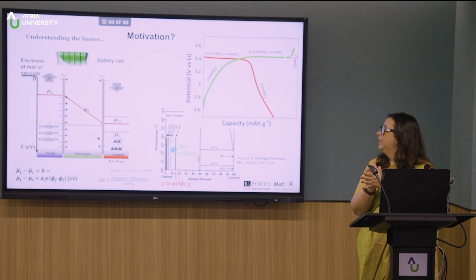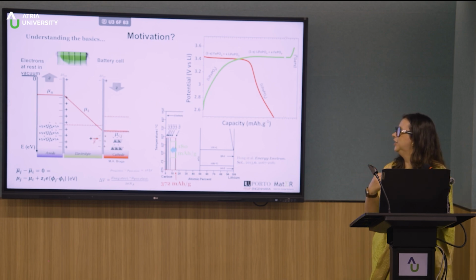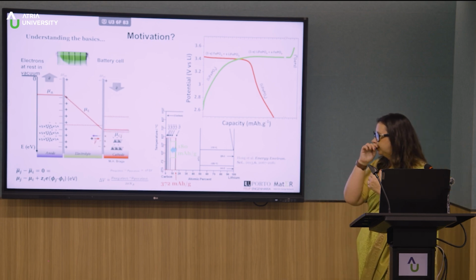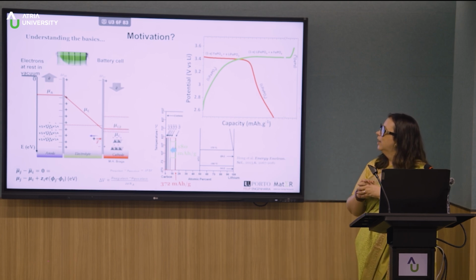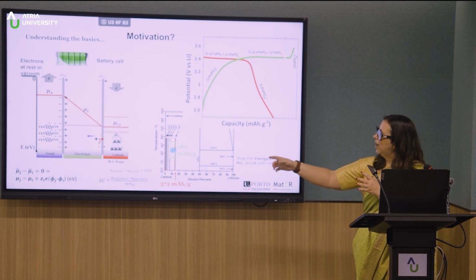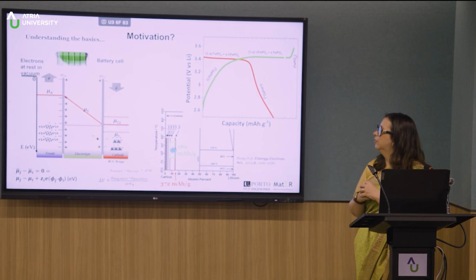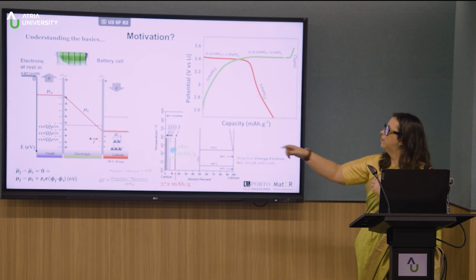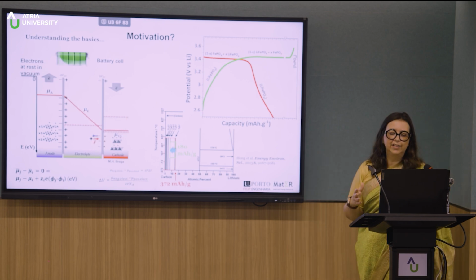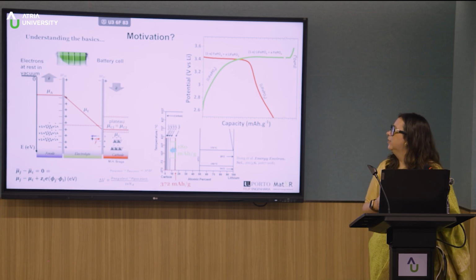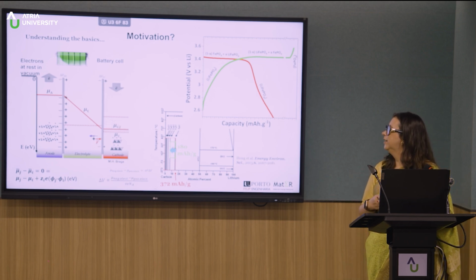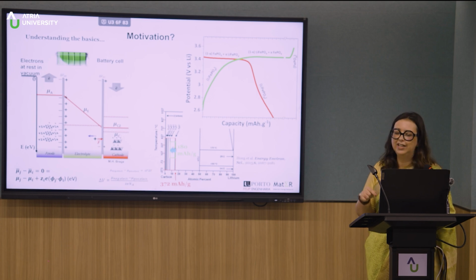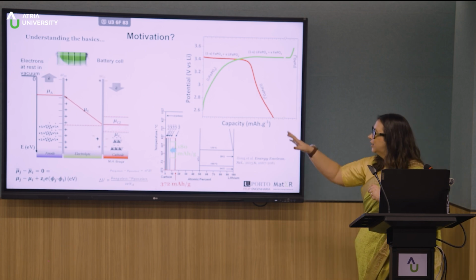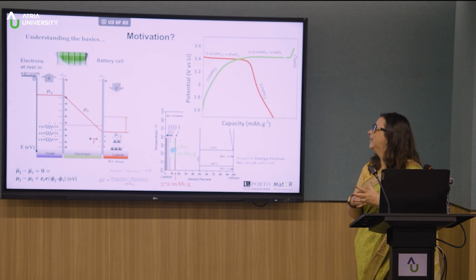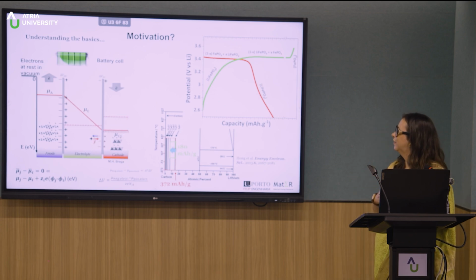And how is that done if we have an insulator that cannot receive or donate electrons without, of course, an external energy? That happens by forming a double layer capacitor. In this equation, you see that a double layer capacitor must form at the interfaces when you have an insulator. And that's where the energy actually is in a battery. So the energy is in that double layer capacitors that form at the interface.